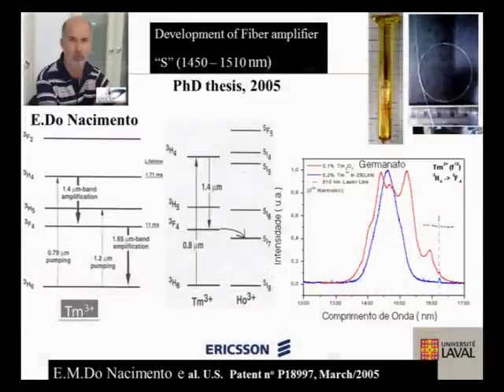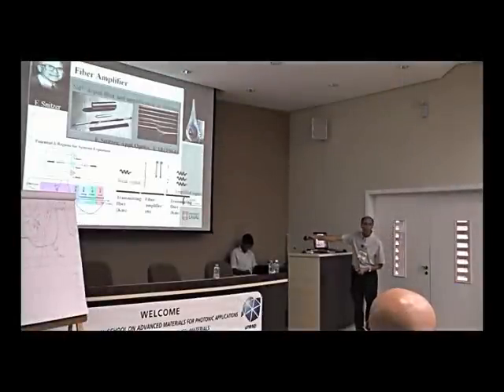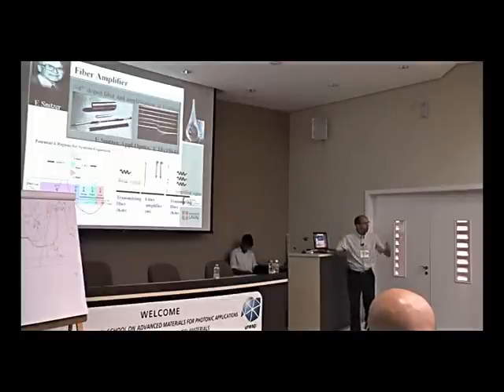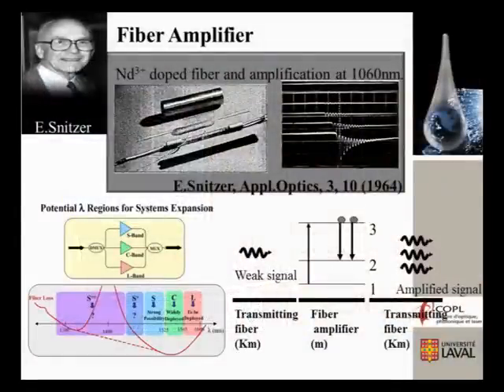Of course, at Araraquara in 2005, in the PhD thesis of Eduardo, we worked with Ericsson on developing another kind of optical amplifier. Our challenge with Ericsson was the S-band, around 1.40 micron. At 1.40 micron, we looked for the rare earth element that allows us to get emission at 1.4. In this case, you can adopt silica, but the emission efficiency is too low, and we looked to develop a new kind of glass. This is the work developed by Eduardo in his thesis.